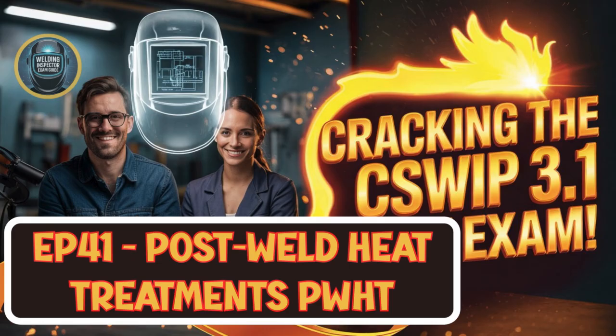For local PWHT, the procedures need to specify even more detail, not just the time and temperature cycle, but also things like the exact width of the heated band around the weld. That's the zone that must reach the full soak temperature. And they also specify the width of the temperature decay band, the area next to the heated band, where the temperature needs to gradually and controllably drop off down to that 300 C mark or so. So you control the temperature profile across the HAZ, too.